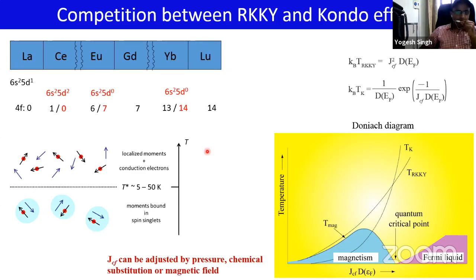So in ytterbium, for example, what happens is that at high temperatures, we have these localized ytterbium moments in a sea of conduction electrons. The localized moments are the ones with the red sphere, and the blue arrows are the conduction electrons going around. So at high temperatures, we have these two uncoupled entities. But as we lower the temperature, because of Kondo hybridization between the conduction electrons and the local impurity, we end up with singlets.